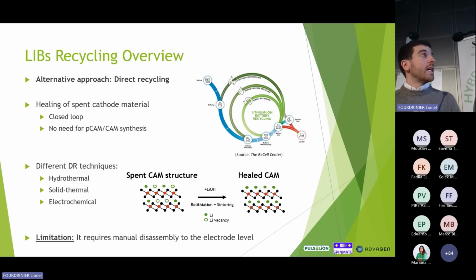So this approach is very interesting. But the main limitation is that to be able to apply the direct recycling, you need to have a very pure cathode material as entry material. And this is not possible if you have a mechanical pre-processing because you will have cross-contamination. So right now, the only way to obtain a pure cathode material to be repaired is by disassembly to the electrode level. And this is only possible manually because right now it's not possible to do the automatic disassembly of the cells to the electrode level because there is a huge variety of cell configurations, module configurations, and so on. So that's why this technique is currently limited to the lab scale.